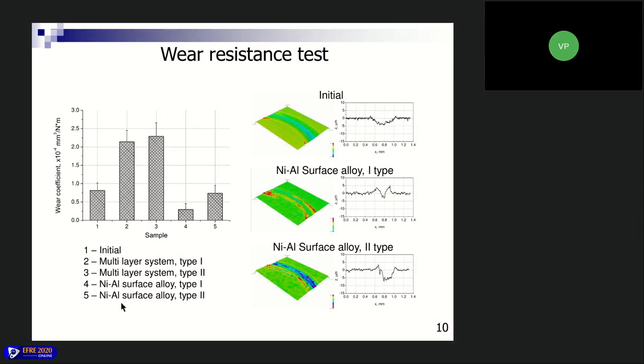The next slide is about the wear resistance tests. The tests were conducted for 5 samples: the initial one, number one, and the 2 multilayer systems with quite the same results of quite a high wear coefficient. And for the surface alloys, we can see that the wear coefficient is significantly lower than for the multilayer systems, and for surface alloy type number one, it is 2.5 times lower than for the initial sample. These tests were made by a pin-on-disk system.